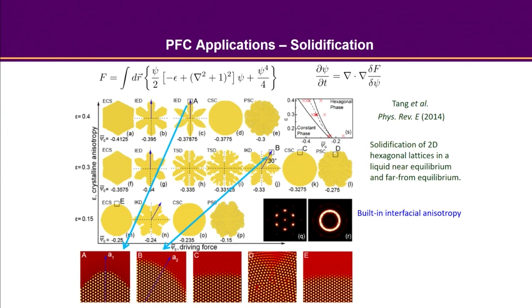Okay, so we were talking about how, if the driving force is small, the shape is still determined by the surface energy and anisotropy. But if we further increase the driving force, like case B showing here, it starts to prefer a different growth direction. Their interpretation is that it's kinetic anisotropy control. So by just changing the driving force, the system can switch from capillary anisotropy driven growth to kinetic anisotropy driven growth. That's the example they are showing here. But what's more interesting is actually case D here, if you really have a very strong...